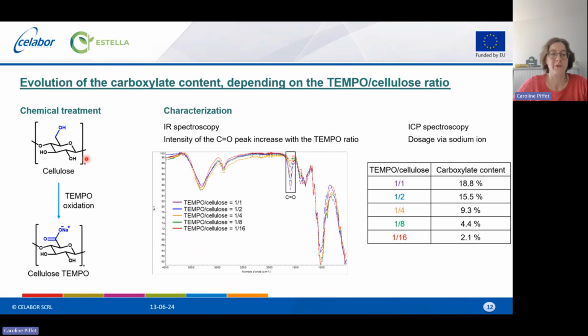So we have, as a reminder, this functionalization with carboxylate groups grafted on the cellulose, and we varied the TEMPO reactant ratio by decreasing from the ratio we used at the beginning. We call this 1:1, and we decreased up to 16 times this ratio. And you can see in the IR spectroscopy that we have the carboxylate groups decreasing.